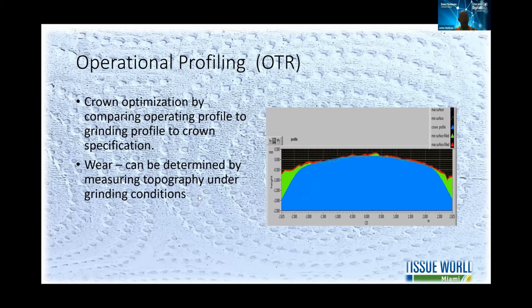It can also tell you if there's any wear on the surface, because we don't know for sure sometimes if it's operating conditions or wear conditions. So by measuring under grinding conditions, we can separate the two and determine exactly how much wear the Yankee dryer has.